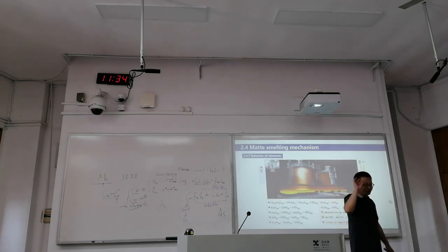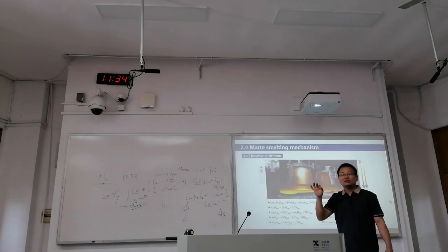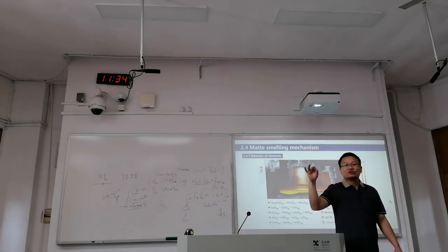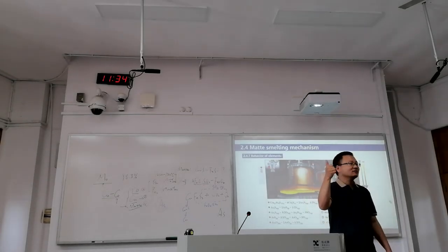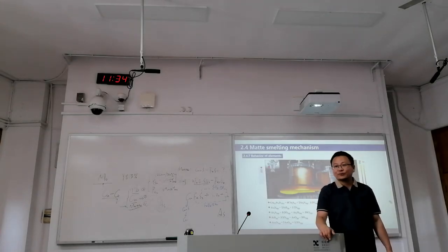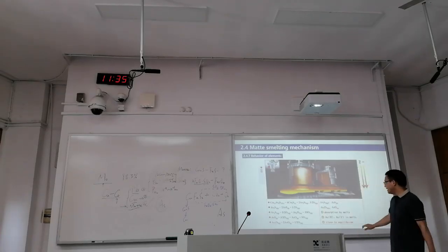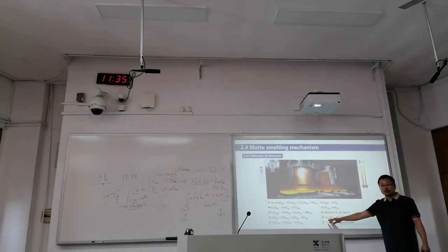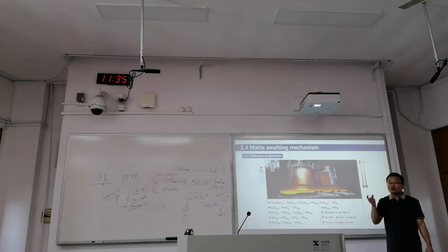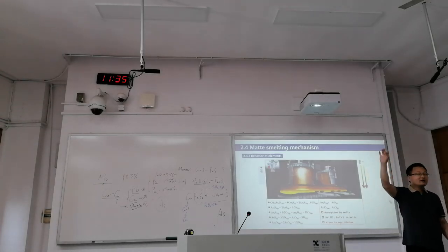When we're having numerous droplets of melt and slags, the interactions between gas and droplets will be very good. So there is one good way for the dissolution. Arsenic is in the gas, right? Yes. The gas is surrounded by droplets of melt, droplets of matte, or droplets of slag.